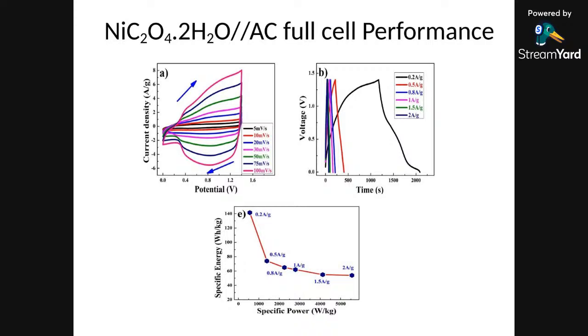So as I told you, now we want to make a composite or a hybrid supercapacitor. So we have taken activated carbon, which works like an EDLC electrode, due to high surface area, high storage you can get in activated carbon with capacitor-like performance. And then when we have taken activated carbon as a counter electrode or negative electrode and nickel oxalate as a positive electrode, we have done the cyclic voltammetry or charge discharge. Now you cannot see the distinct redox peak. However, we still can get very high energy and high power together.